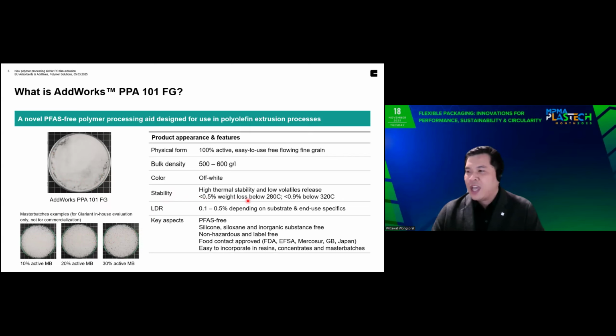The thermal stability of the product is quite good. At 280 degrees Celsius, the weight loss is less than 0.5%. At 320 degrees Celsius, the weight loss is about 0.9%. So in terms of the processing window, we can apply it in blown film application and also cast film application. The recommended dosage is in the range of 1,000 up to 5,000 ppm, depending on the polymer type, the process, and the customer's target use. For normal blown film application, we recommend 1,000 up to 3,000 ppm.